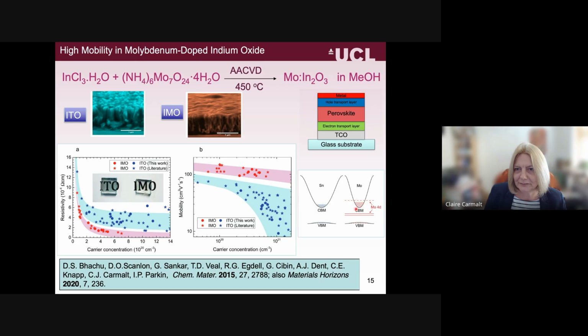And we did a lot of computational studies. I'm not a computational chemist, though, but essentially we were able to show from the computational studies that this related to the molybdenum 4d state sitting quite high up in the conduction band minimum. And so essentially what you get with the molybdenum doped species is a higher mobility and therefore a higher conductivity with the same carrier concentration. And so we were able to show you could use much thinner films of IMO to get the same properties that you need for the ITO.